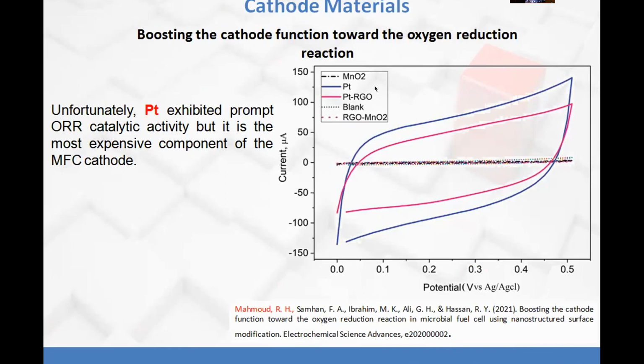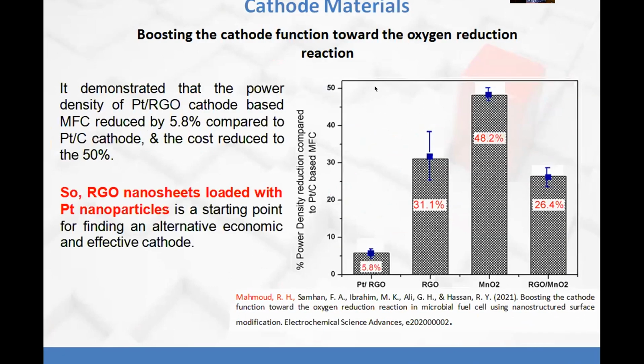Okay, on the cathode side, it's important to boost the cathode function toward the oxygen reduction reaction, but unfortunately, platinum, which is the most common catalyst, is very expensive, and so we use reduced graphene oxide nanosheets loaded with platinum nanoparticles. It was demonstrated that the power density produced by this microbial fuel cell was reduced by only 5.8% compared to the pure platinum cathode, and the cost was reduced to half. And so, reduced graphene oxide nanosheets loaded with platinum nanoparticles are a starting point for finding an alternative, economic, and cost-effective cathode material.